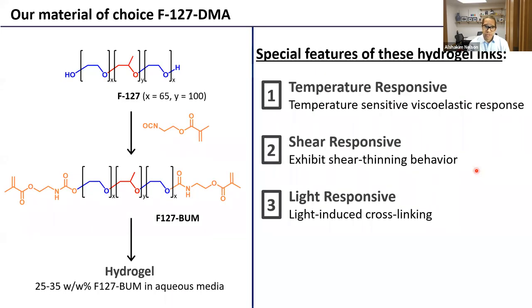Our material of choice we refer to as F127 BUM. I'm sorry, it says DMA here, but it should be BUM. We start with a commercially available tri-block copolymer known as F127. This is a pluronic. We just do a one-step modification of the chain ends to introduce methacrylate groups onto the two termini. If you take this polymer and dissolve it at 25 to 35 weight percent in water, you get a hydrogel. What's important is that this hydrogel is stimuli responsive in several ways: a temperature response, a shear response, and a light response. The combination of these three is what allows us to print these into three-dimensional structures that we can use for biocatalysis.